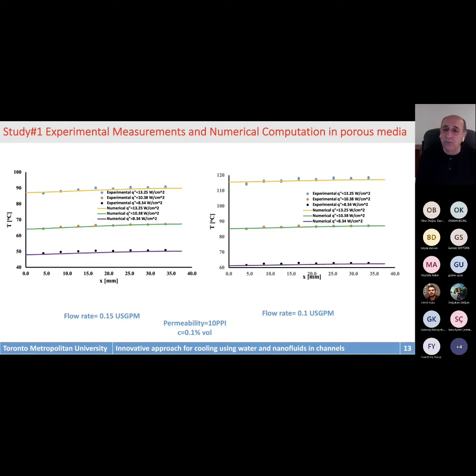So we are heating the bottom of the block, and we detect the temperature at the interface between the heated block and the channel where the fluid is moving. So we did it for a flow rate of 0.15 US gallon per minute, 0.1 US gallon per minute, and this is the result for nanofluid. And the concentration of nanoparticles here was 0.1% volume. And we had a good agreement between experimental and numerical.